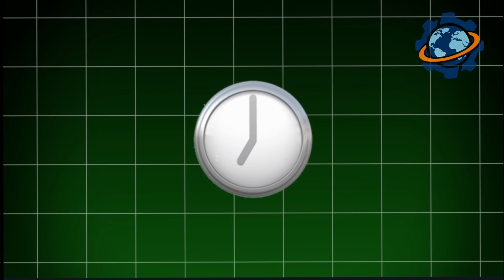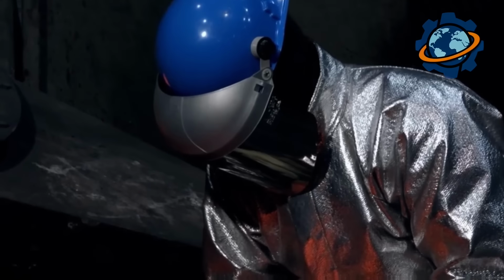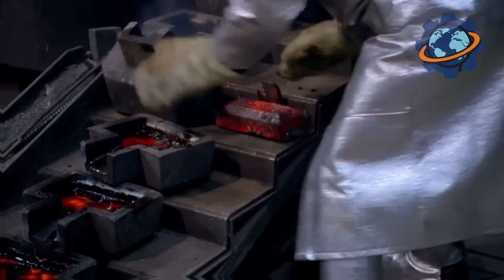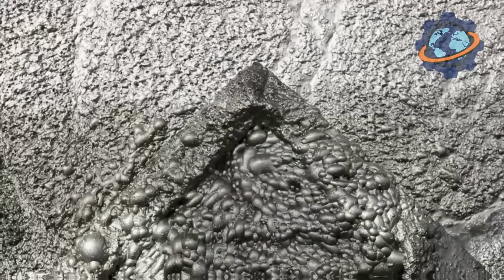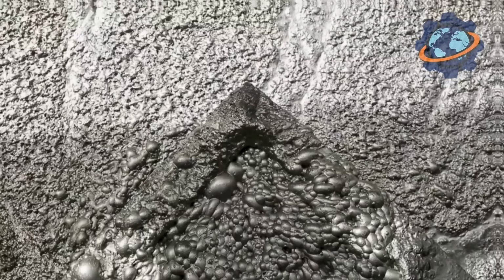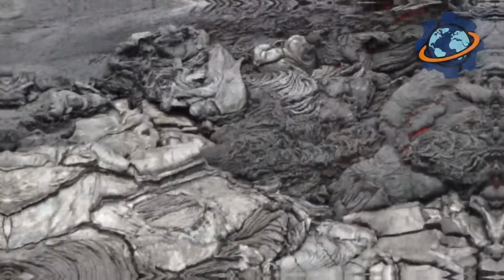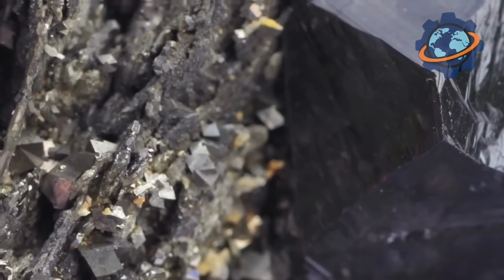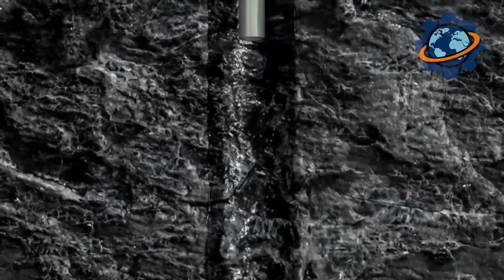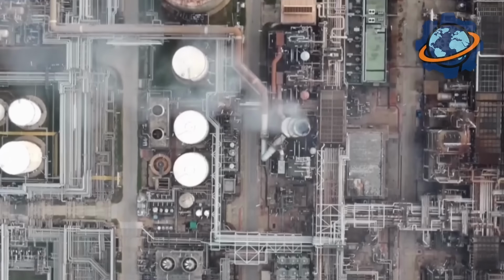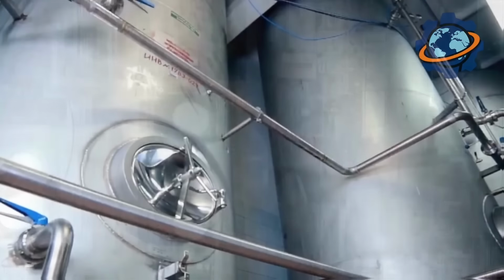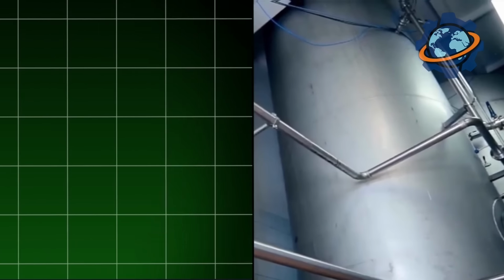The beam is held in the bath for 1 to 2 minutes. Then it's pulled out. Excess molten zinc drains back. In air, the coating quickly solidifies. The surface becomes silvery, matte, with the characteristic pattern of crystals, zinc flowers. Coating thickness from 2 to 8 thousandths of an inch. That's just fractions of an inch, but it's enough. The galvanized beam won't rust for 50 to 70 years. Even scratches aren't scary. Zinc continues protecting.